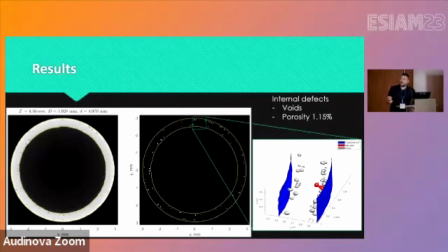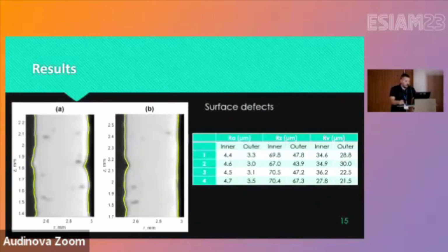It is. And here are some voids. Basically, the porosity was not so big. It's 1.15%. And for the surface defects, we also used the tomography to calculate the exact thickness of the wall, which was a little bit below 0.5. And as you can see, in all cases, Ra, Rz and Rv, the inner surface is worse than the outer surface.